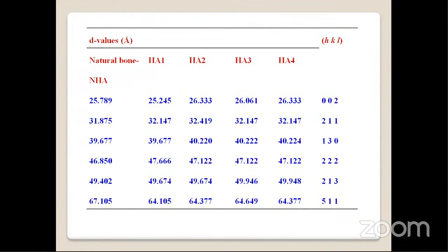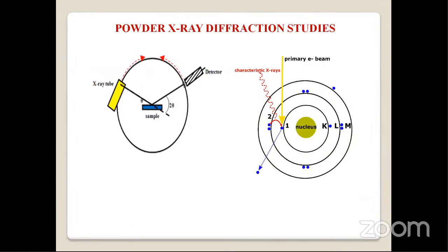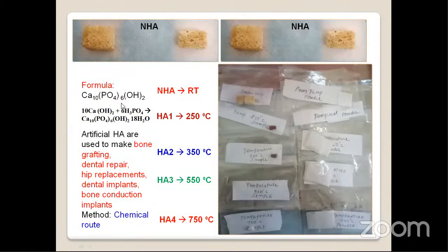Chemical synthesis. This is the chemical synthesis formula. Actually, we are taking 10 mole percentage of calcium hydroxide and 6 mole percentage of phosphoric acid, hydrogen phosphoric acid. So with this, one can change the calcium part or the phosphoric acid part. For example, one can take 8 mole percentage of calcium and 2 mole percentage of titanium nanoparticles, so that one is able to synthesize titanium-based hydroxyapatite materials.